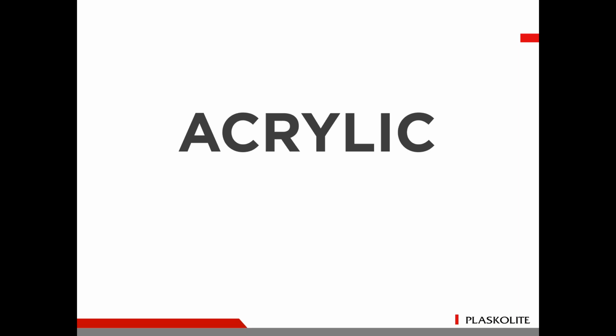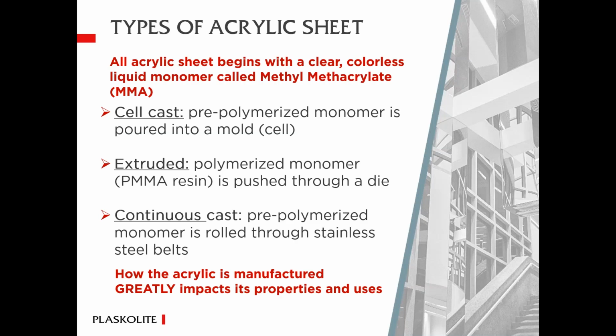So let's go into the acrylic side of this. There are three different types of acrylic sheet that we see domestically here pretty regularly. All the acrylic sheet begins with a clear liquid called MMA, or methyl methacrylate. What happens is that you do a pre-polymerization monomer in there, and you pour it into the mold or into the extruder, and then that would come out with a sheet.